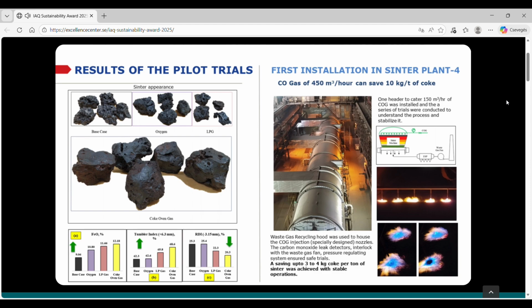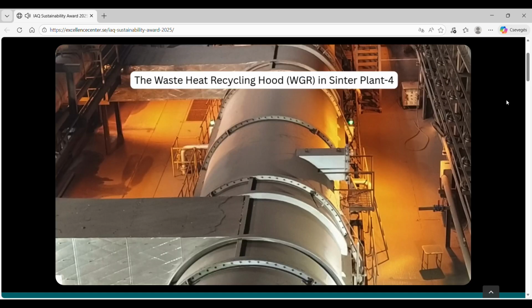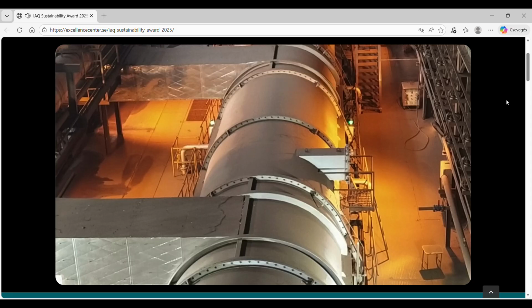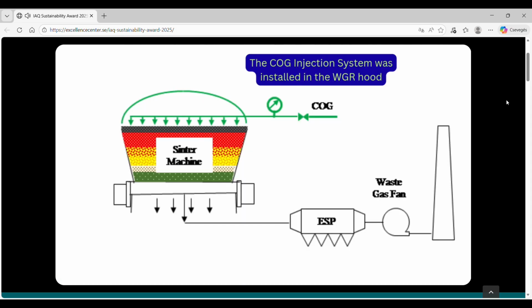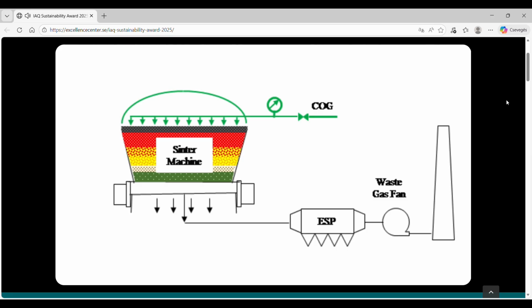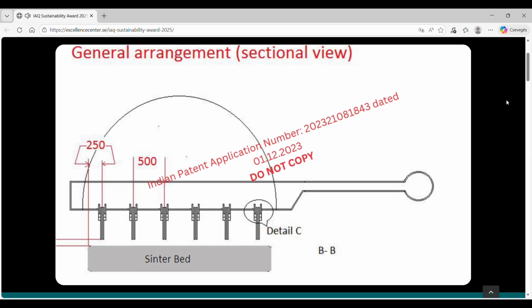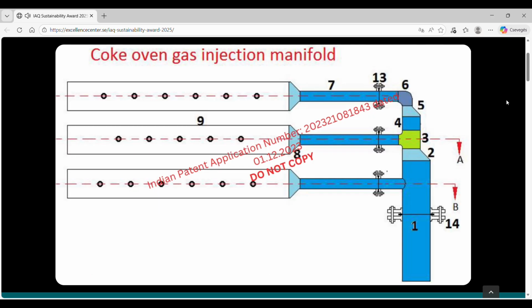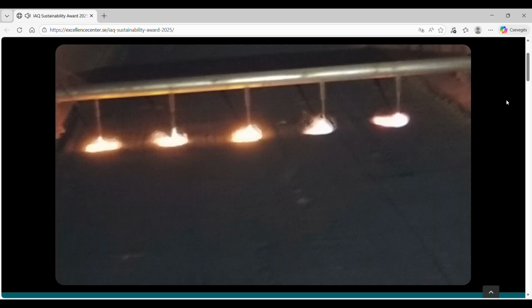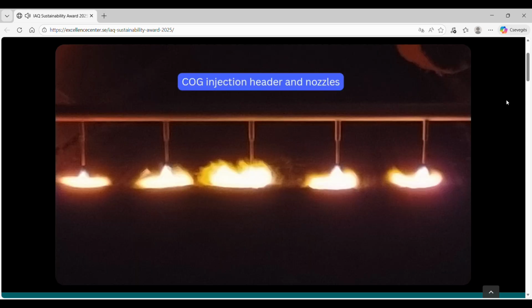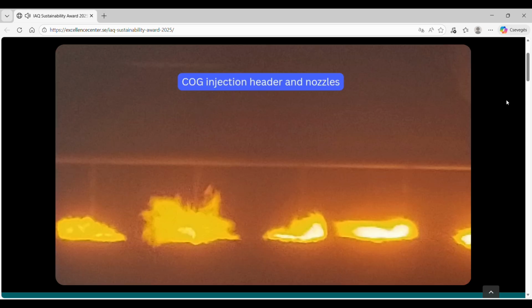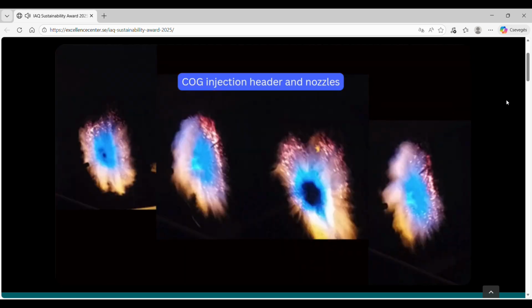After proving the concept, we scaled up by designing COG header, nozzles, and installed in Sinter Plant 4 in 2020 during COVID times. This is the scheme of the injection system. The design involved 3 headers of 150 cubic meter per hour capacity each and nozzles to inject COG close to the sinter bed. Multiple trials were conducted to fine-tune the process, and we continued injecting for more than 1.5 years.